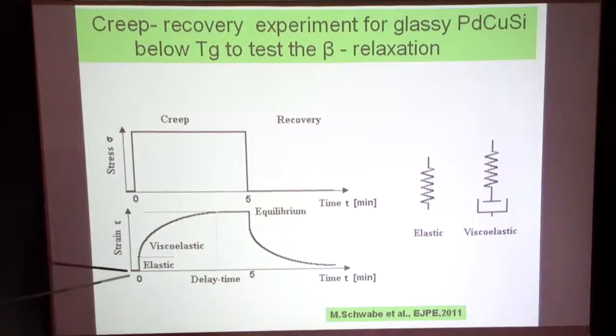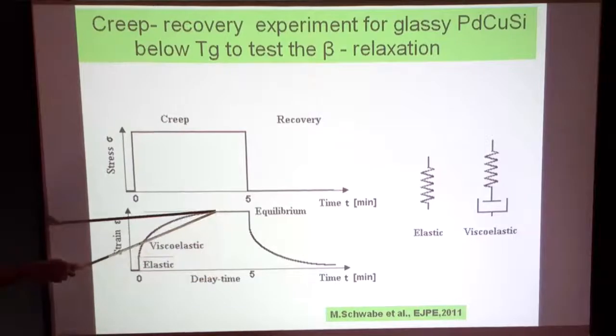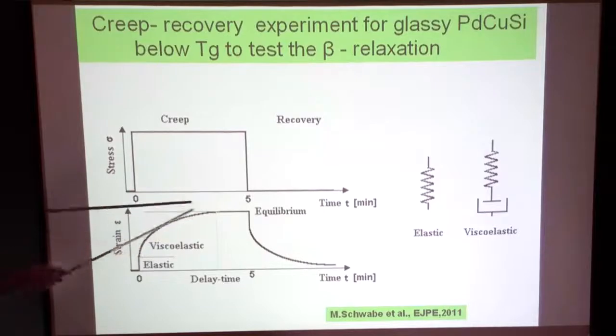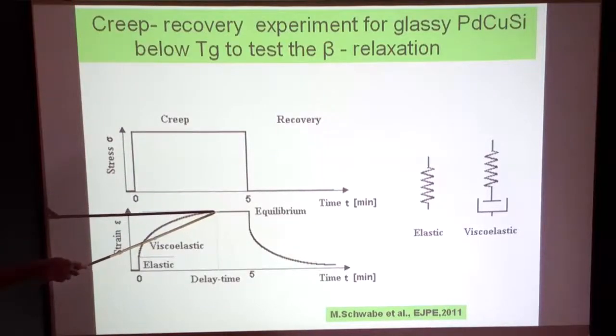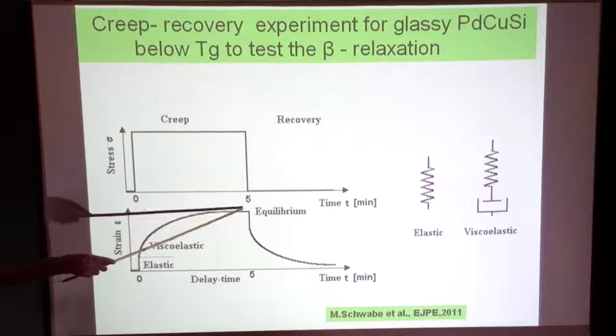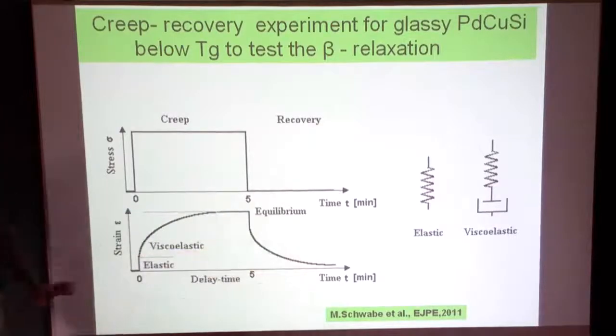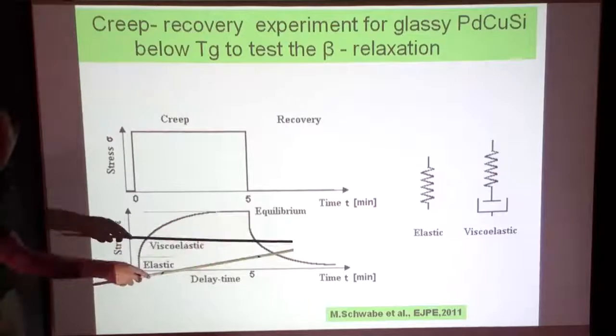Normally you would say, okay, there is an elastic jump in the strain, and you wait for a certain time, depending on what we call sometimes delayed time, which is just a time where it reaches some kind of equilibrium, which is a matter of the loss which you have in the system, how much you dissipate in the system. Takes a certain time, you wait, and it comes back, and should be the same one. In a system which has no dissipation, these two curves are the same. Later on, I show you that on this flank we see the avalanches. On that one, we don't.